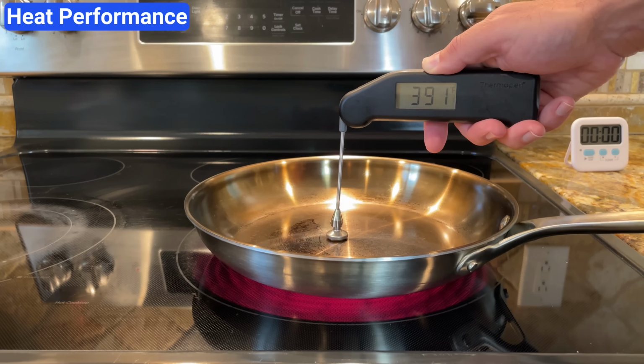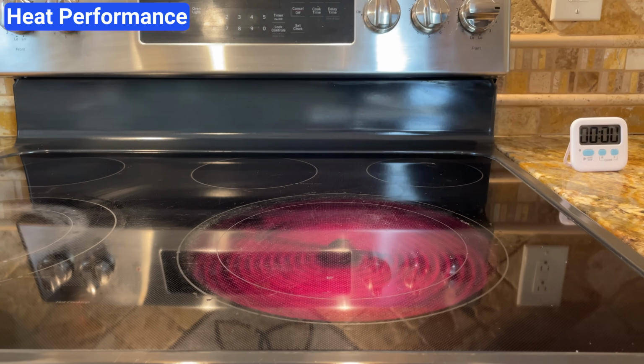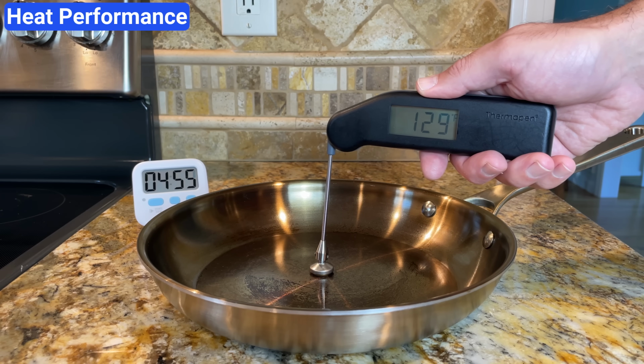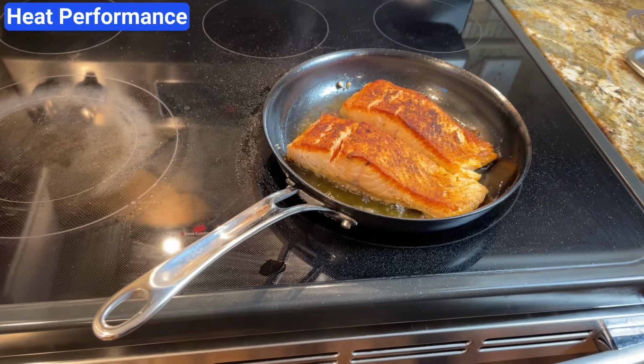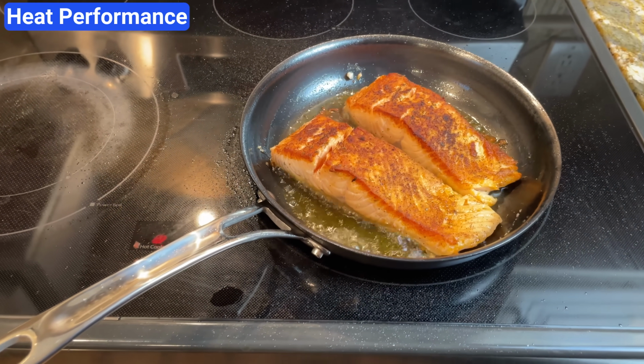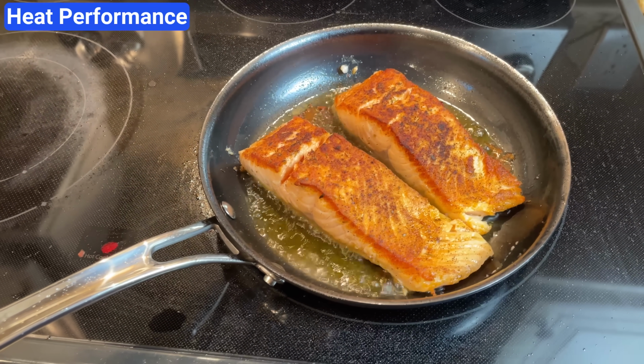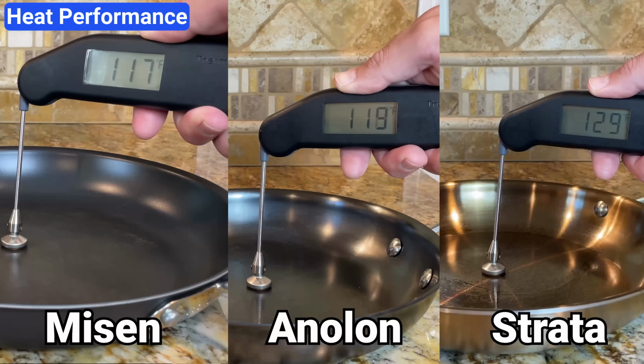To measure heat retention, I heated each pan to exactly 400 degrees Fahrenheit, removed them from the burner, and measured the surface temperature after 5 minutes. These pans are designed to be lightweight and easy to use. They're not optimized for heat retention like thicker carbon steel or cast iron pans. But within this group, Strata held its temperature the best by about 10 degrees.